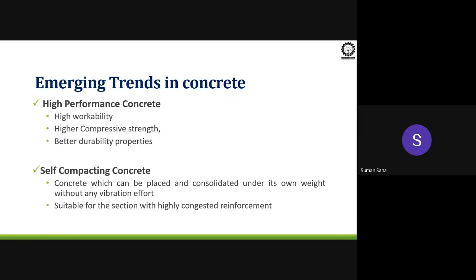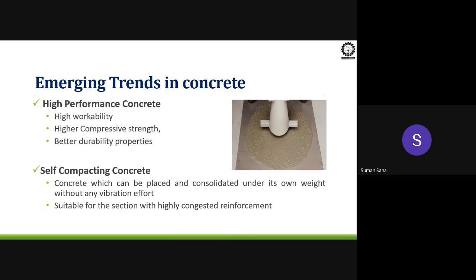so that without any vibration the concrete section can be cast, and it will be compacted by its own weight without any segregation, without any water evaporation. So it is a very important type of concrete for highly congested reinforcement sections. If you see here one photo, I have shown how the self-compacting concrete works with a slump cone. If you put the concrete and lift the slump cone, the concrete will flow out on its own